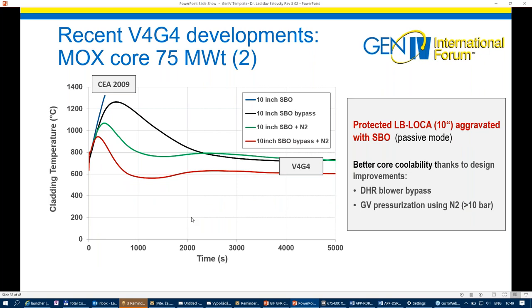Here we see a similar picture in case of a large break LOCA characterized with fast depressurization. So in 2-3 minutes, the original concept would reach stainless steel melting in the core. In our case, the introduction of the bypass of the decay heat removal blower would already well prevent the melting of stainless steel in the core, and in association with the injection of nitrogen into the core, here individually introduction of bypass and individually introduction of the nitrogen injection into the system.